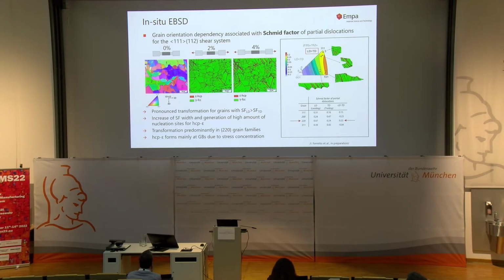And we made an interesting finding from in situ EBSD measurements. So here you see grains that are indexed, with regard to our color scale below. And my PhD student, Irene, calculated all the Schmid factors. And what we could see here, we looked into certain grains. Everything that is blue, so these grains, here the Schmid factor of the leading partial dislocation is always larger than the Schmid factor of the trailing partial dislocation. And so this is consistent.